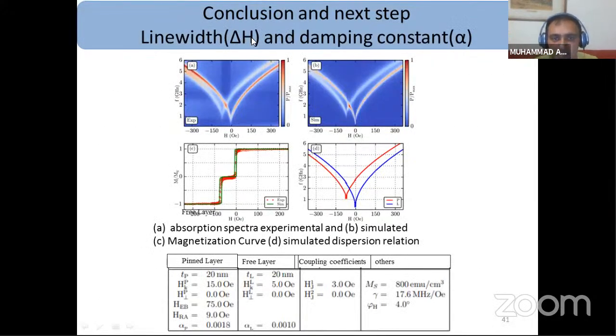Here, the further step will be to measure the line width and damping constant of our magnetic systems. By fittings, we can get the coupling constant and different magnetic parameters. Here in a static curve, you can see a free layer is switching independently from the reference layer. From our fittings, we have got the coupling coefficients like 0 and 3 oersted, which is expected since the free layer is switching independently.